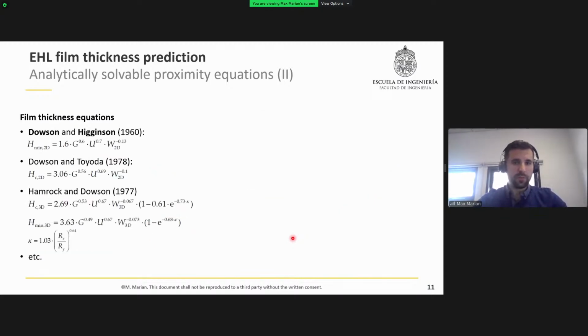To estimate, for example, the minimum film thickness in an EHL infinite 2D line contact, Dowson and Higginson proposed an analytically solvable regression equation as a function of the material, the velocity, and the load parameters. And based upon more advanced isothermal EHL simulations, these parameters have been modified and extended by various authors to also cover 3D point contacts and also allowed the determination of the central film thickness.